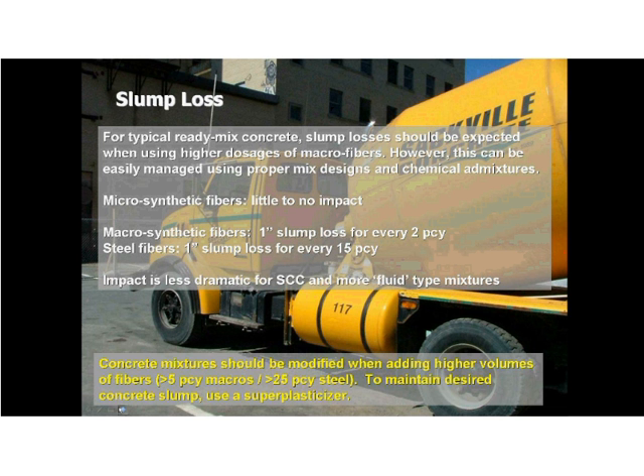For projects that are requiring high volumes of fiber, such as 5 pounds of macrosynthetics or 40 pounds of steel fiber, you can have significant slump loss, which does need to be accounted for in the mix design. Your concrete producer needs to be aware of this, and they need to provide you with something that can still be placed or pumped and finished with ease.